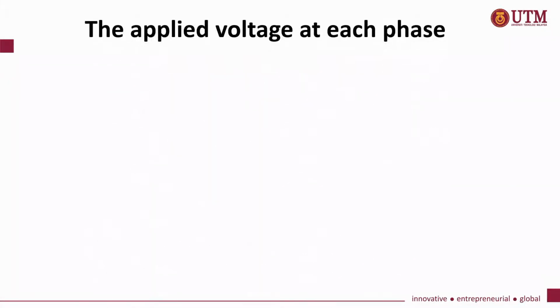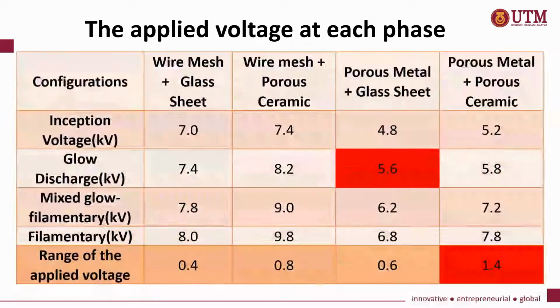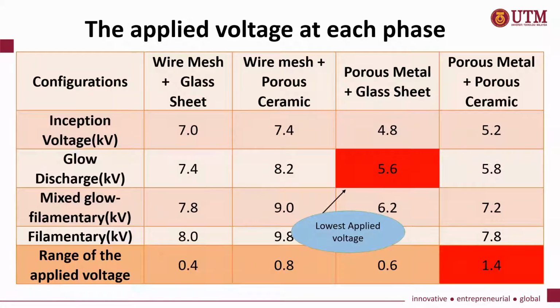The voltage at each phase for each configuration was tabulated in the table, based on the results obtained from the Lissajous figure and also the voltage discharge current waveform. We can see that the configuration with the porous metal as metal electrode and glass sheet as dielectric has the lowest applied voltage to initiate the glow discharge plasma. As reported in the literature review, an appropriate hole size of the metal electrodes, approaching the mean free path of the feed-in gas, is believed to produce a more stable glow discharge at atmospheric pressure.